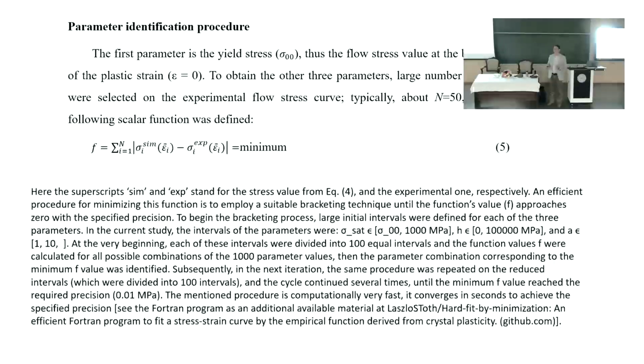And for each you get a value, and then just choose the minimum one. You already have 100 times smaller approximation, you are at the right value. Then again it's not sufficient because it's only 1 percent perhaps. We can go further. The new interval, we divide again into smaller ones. It's a rapid process - in 1, 2, 3, certainly less than 5 iterations, you get the result.